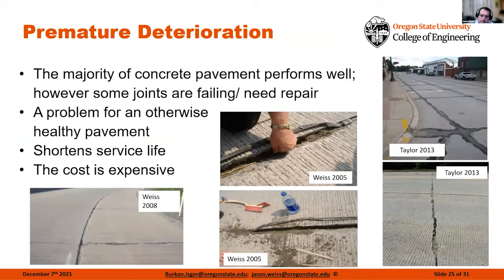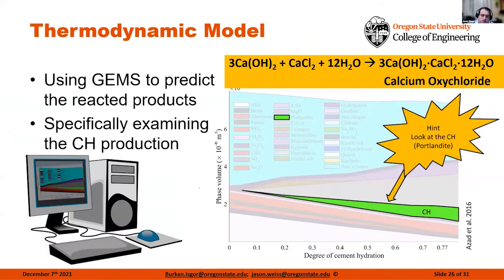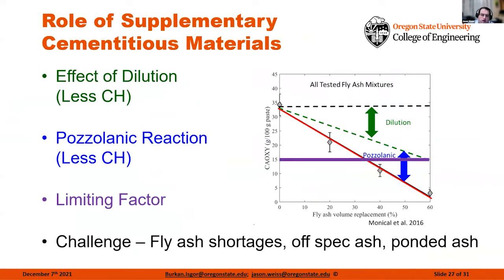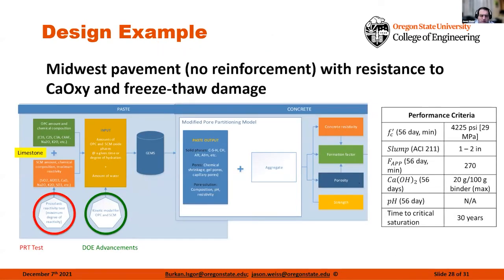So I can go through and I can say, I've got a pavement. I have to design it for de-icing salts. How do I design this material? Well, I focus in on minimizing the calcium hydroxide in the system. The way that I do that is I use more and more SCMs. By using those SCMs, I reduce the amount of calcium hydroxide by diluting the cement that's in the system, but I also get this pozzolanic reaction that's taking place. And now I can actually design my system with the right amount of SCMs so that it has a long-term durability.